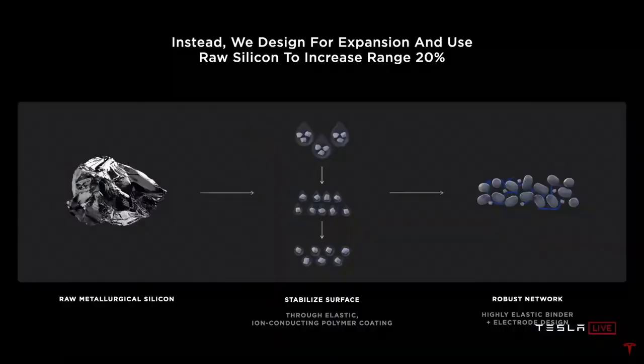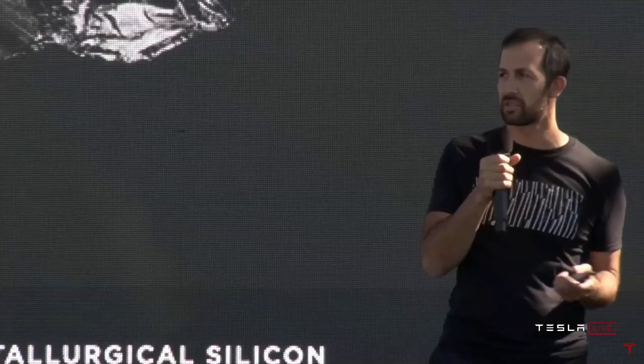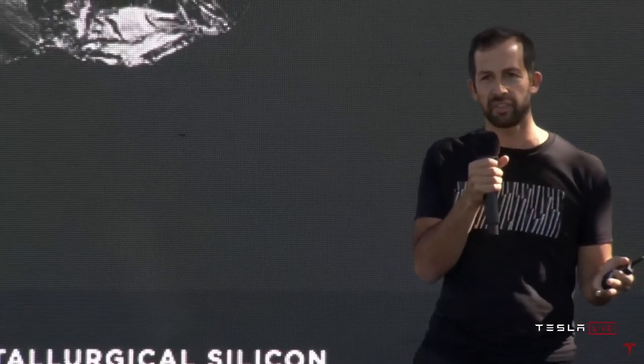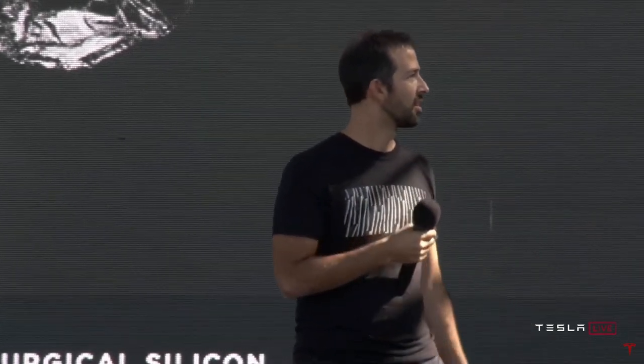And how does it work? Start with raw metallurgical silicon, stabilize the surface with an elastic ion conducting polymer coating that is applied through a very scalable approach. No chemical vapor deposition, no highly engineered, high capex solutions, and then integrated into the electrode through a robust network formed out of a highly elastic binder. And in the end, by leveraging this silicon to its potential, we can increase the range of our vehicles by an additional 20%, just this improvement. Yeah, it gets cheaper and longer range.